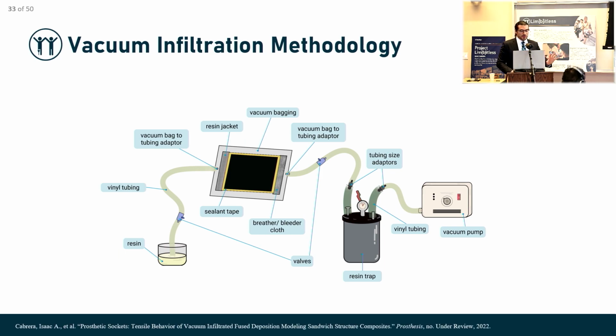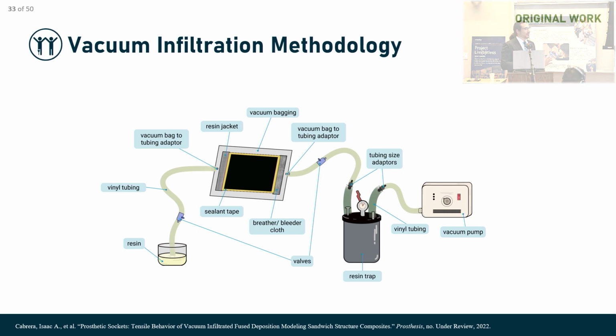So we created a whole new vacuum infiltration methodology for manufacturing our materials. We were able to 3D print test sheets, but those test sheets served as molds, which we then filled with resin. This reads from left to right, where we had a resin, a bunch of tubes, and a vacuum sucking it all through, and things like this resin jacket, and what else? The breather and bleeder cloth to make sure that the resin is dispersed as evenly as possible, to try not to have so many porosity defects. So we took a lot of consideration in this vacuum infiltration methodology.